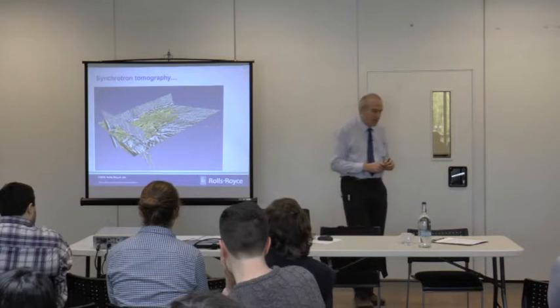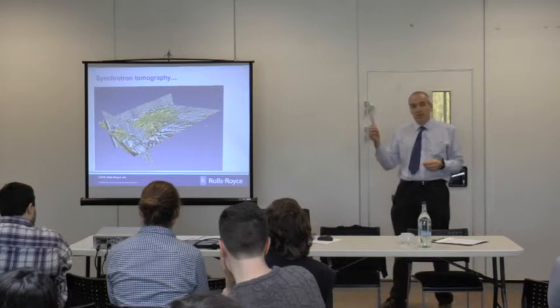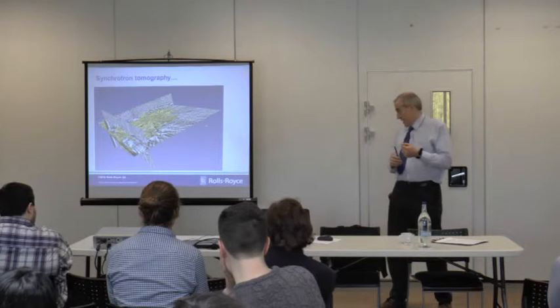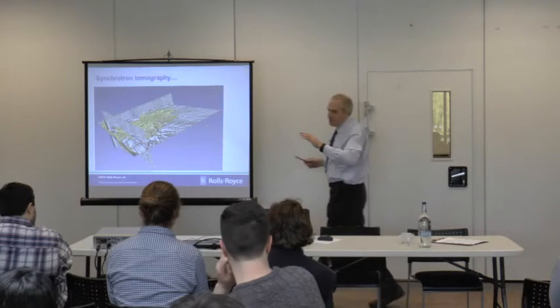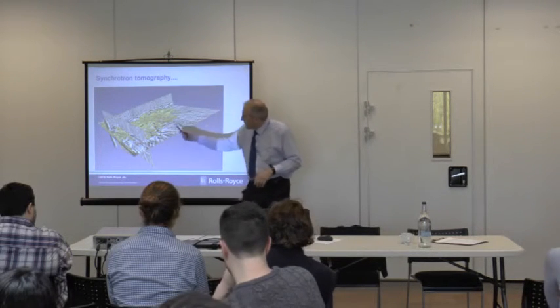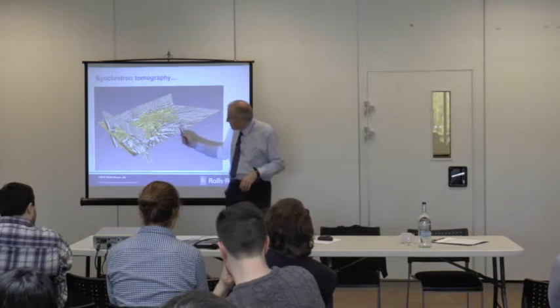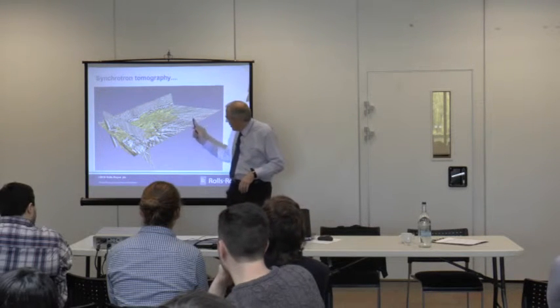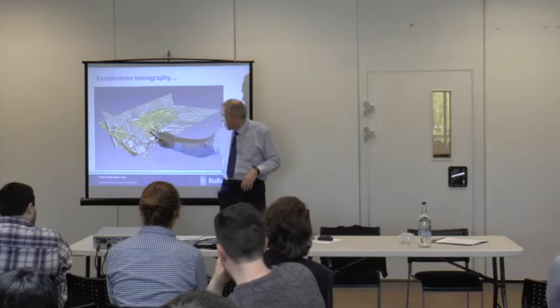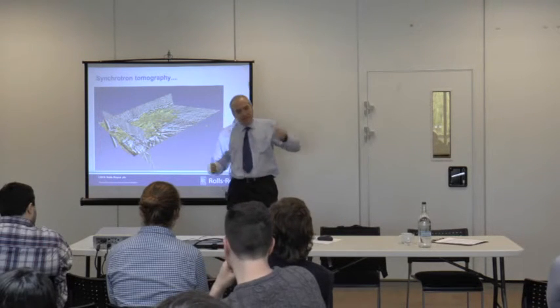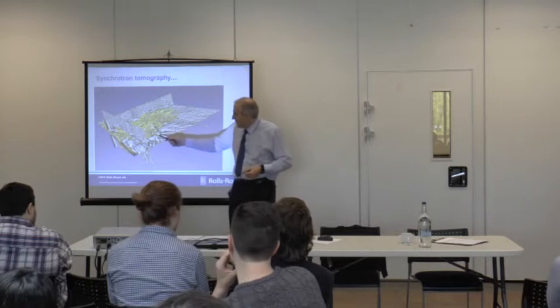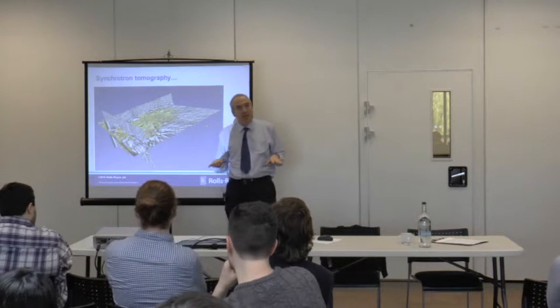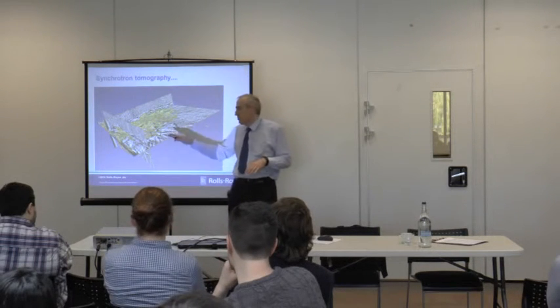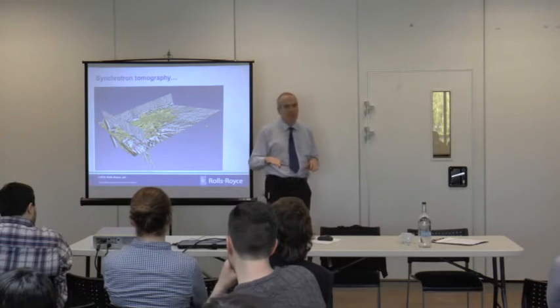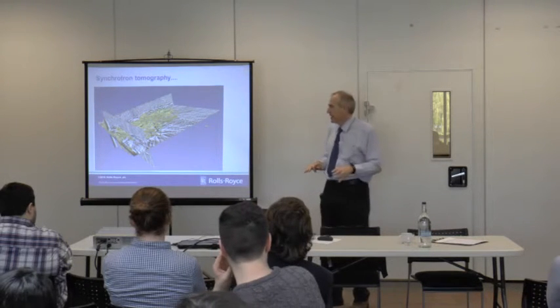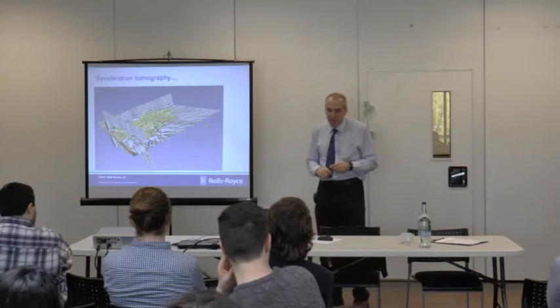So several different things you can do. At first pass, you can have some great fun putting in situ loading rigs inside synchrotrons. You can do tomography, so you'll know more about that than I. So this is actually a crack front. You get phase contrast imaging, so the light and grey there is actually the microstructure of the metal. You load the thing in different ways, you pull it around and wiggle it, and you can watch the cracks propagate and you can see how they interact in 3D. That's important because when they're near the surface, they behave differently because you've got different constraint. So that's actually quite enlightening in its own right.